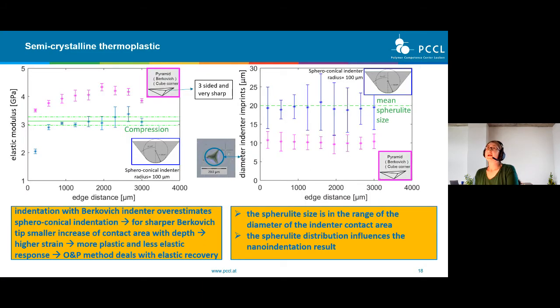So now we investigated this semi-crystalline POM also with another very common indenter tip, which is the Berkovich indenter tip. You can see it here in pink. The Berkovich indenter tip is a three-sided and very sharp indenter tip. And in blue, we have again the spheroconical indenter tip. What we can see when we investigate POM over the cross-section is that the Oliver and Pharr measurements with the Berkovich indenter tip overestimate the values from the spheroconical indenter with the Oliver and Pharr method.